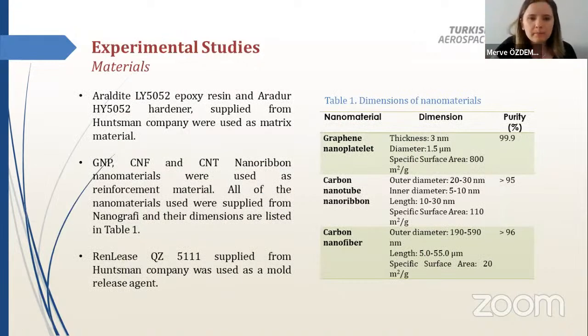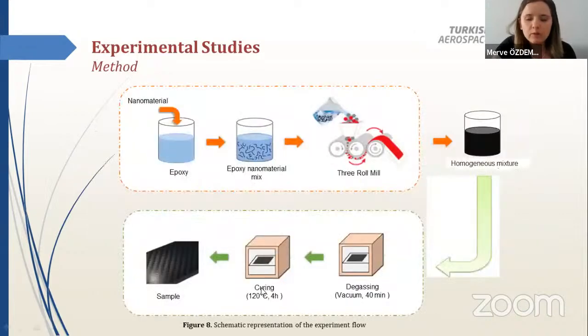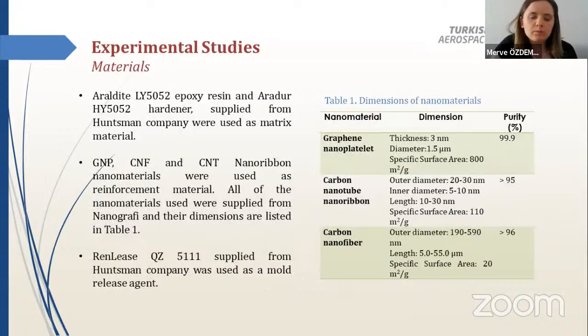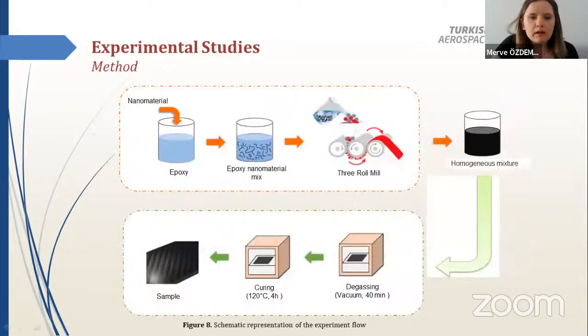Sure. Here you can see the materials used in the study. As nanomaterials, graphene nanoplatelets, carbon nanotubes, and carbon nanofibers were used. In the study, firstly, GNP and CNT were mixed with epoxy resin at doping ratios of 0, 0.05, 0.1, 0.2, and 0.5% by weight using the three-roll mill.